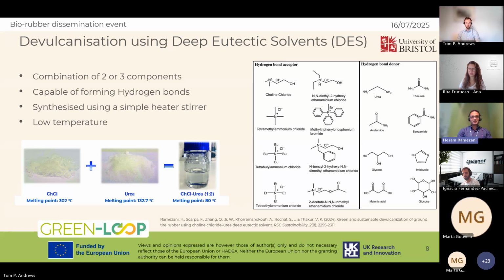Deep eutectic solvents are basically a combination of 2 or 3 hydrogen bond acceptors and hydrogen bond donors, as you can see in the figure on the right-hand side. This enables these materials to form hydrogen bonds between each other, which makes them a very flexible compound to work with. And as a result of that, they can be synthesized very simply by mixing them in powder form and heating them up to low temperatures. In our case, we use choline chloride with a melting point of 300 degrees and urea with a melting point of 130. But after mixing them in powder form, they turn into an odorless and clear solvent at 80 degrees. And the solution is also very stable.